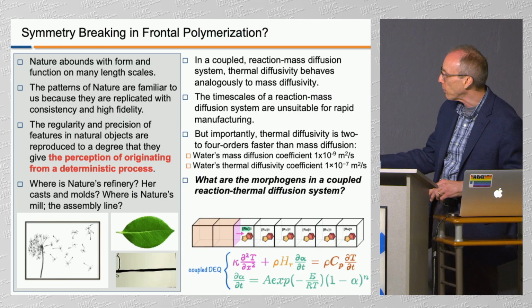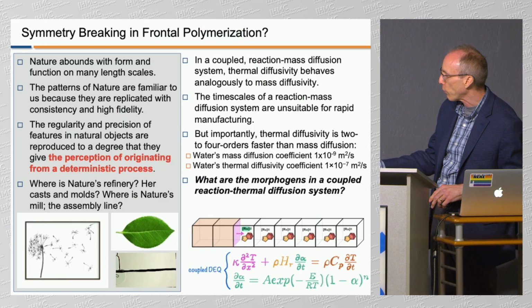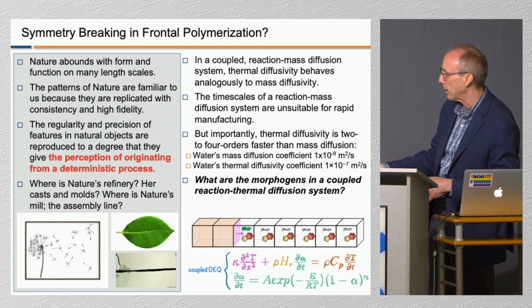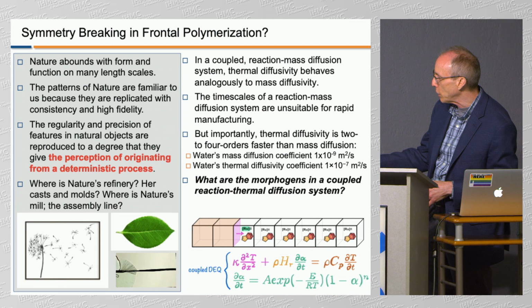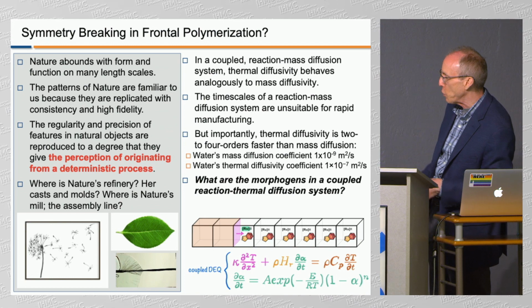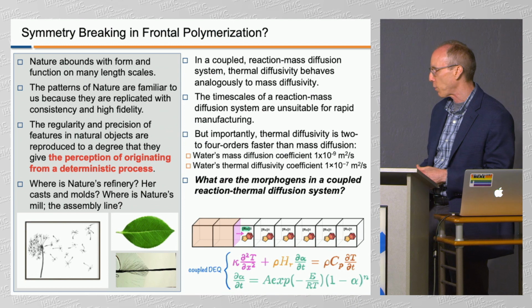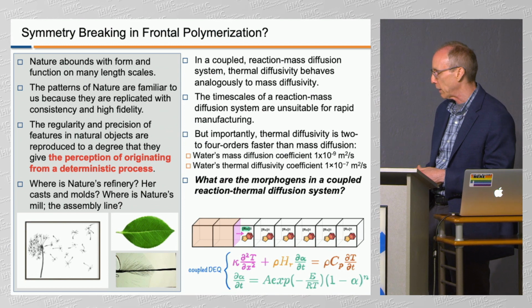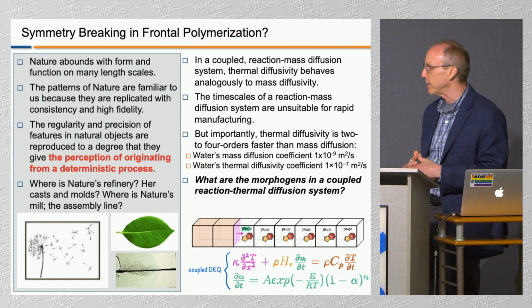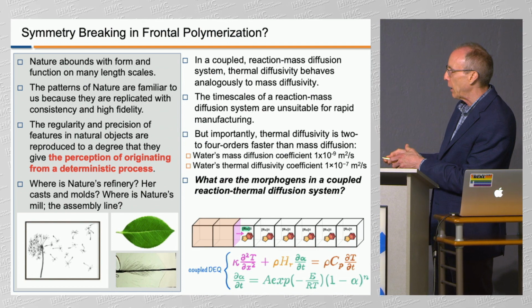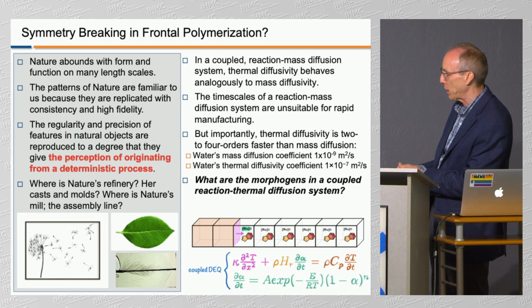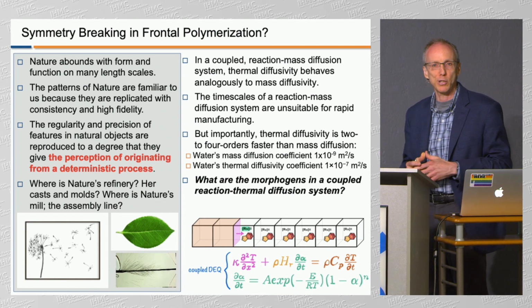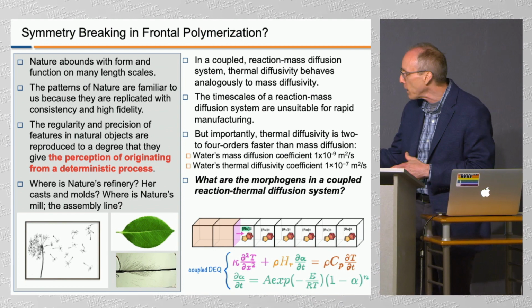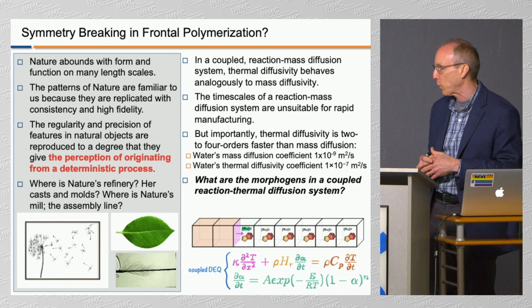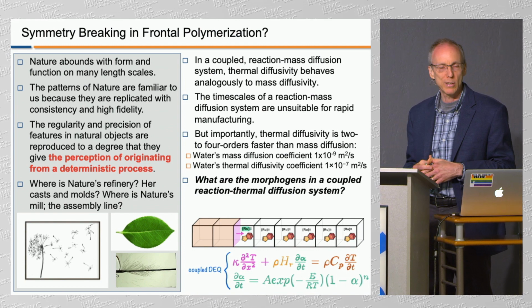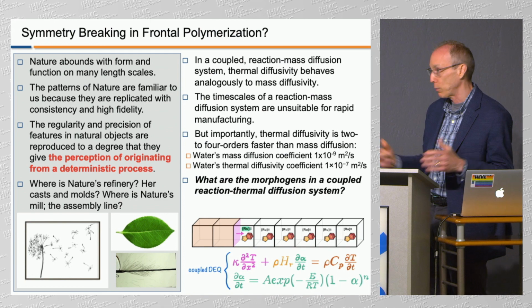And so at the bottom is the only thing I want to draw your attention to, a frontal polymerization that's taking place. It starts with a homogeneous liquid. There's a fiber embedded in it, which is nucleating off that fiber void structures that begin to look like the void structures in leaves. And so we're just being tantalized in the lab with the idea that we're not using any deterministic process to create structure that now is a vascularization that looks very much like a leaf. And we would really be able to, I think, make major progress if we could manufacture components that could take advantage of these symmetry breaking processes.